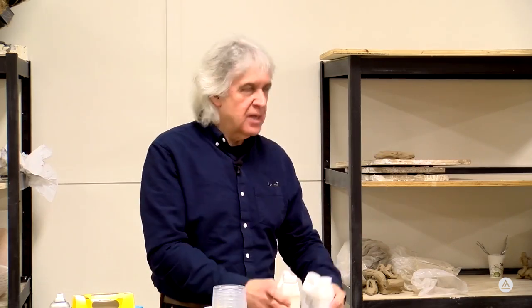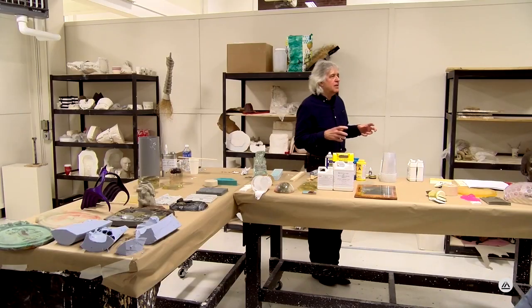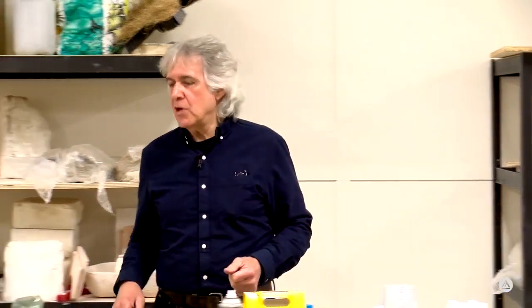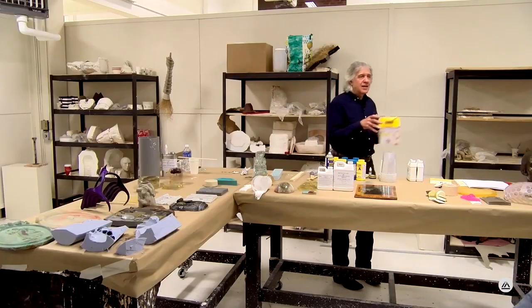If you go outside that ratio, in this case 1 to 1, you're going to get some unpartnered dancers, if you will. So some unpolymerized resin. And so it's going to be either soft or sticky. And it may never cure. I mean, you may have a situation where you've got some product that's been sitting for weeks and weeks and weeks, and it's still soft, and you're going, why isn't this hardening? It's not going to.